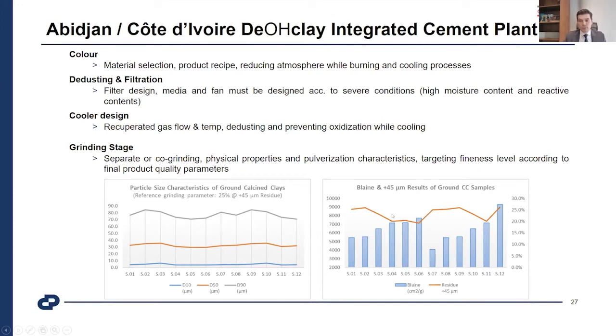It's known in the cement industry, but it's not related to it. Some of the portions pulverize very easily and go to more than 9,000, 10,000 Blaine. But the other portions are left coarse, and it directly affects co-grinding and separate grinding selection. It should be investigated well. That part is critical because it directly affects the concrete rheology and water demand and other stages on the concrete side. We have been working on it for the last 6 months.